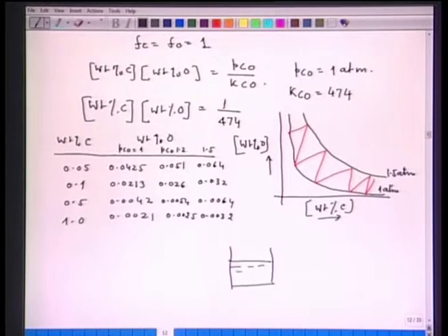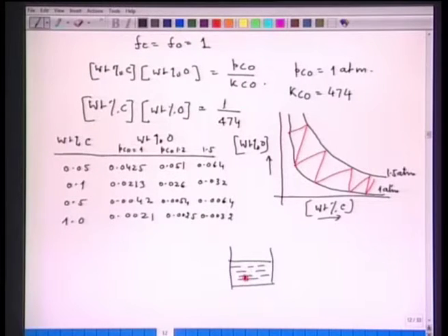This is hot metal, and from here, for example, a nucleation site is somewhere here, and a carbon monoxide bubble is evolved. So, at this particular location, if this is the nucleating site for nucleation of C plus O equal to CO bubble, then the total pressure on this bubble will be P equal to P atmosphere plus this column pressure, that is rho L g H, where H is the bath height.